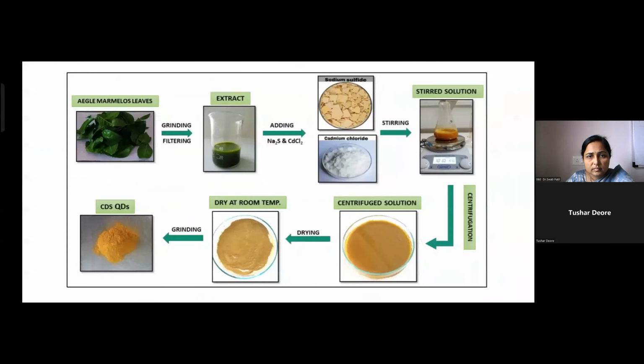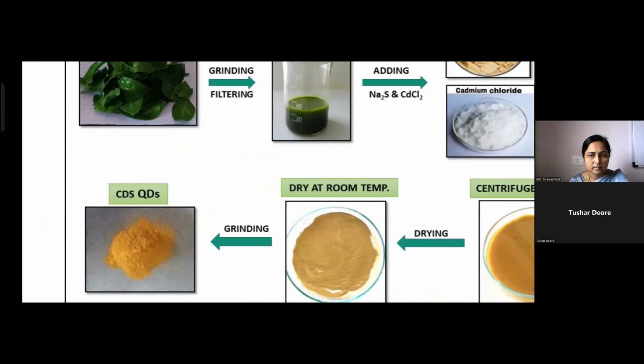In the schematic, we can see that, ma'am, I took the Aegle marmelos and then prepared the extract. The extract was 5 ml, and I added 90 ml of distilled water. In the procedure, 0.2 gram of cadmium chloride was added, and then I stirred at 100 degrees Celsius for 2 hours. After that, I also added 0.78 gram of sodium sulfide, and then stirred for 2 hours. The final yellow-colored product was filtered and centrifuged, and dried at room temperature, and the final powder was used for further characterizations.